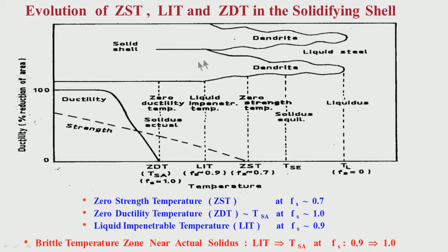So, this temperature zone is really a matter of worry, but fortunately for us, suppose because of the low toughness, some crack formation takes place at this surface. These dendrites, these solid zones, are relatively, why relatively? There is no toughness at all, but it has some strength. So, what is happening is, if due to some strain, external strain or internal strain, whatever might be the source of the strain, because of any force which is interacting with this dendrite, there is a possibility of crack formation.